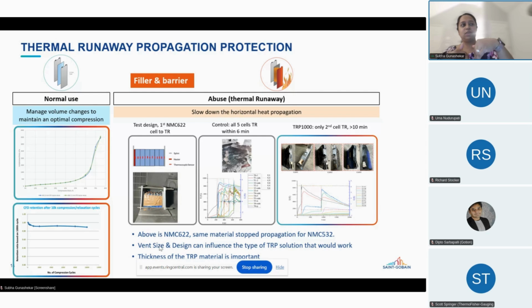So in case of an event, there is still a lot of time for the passengers to get out. So considering all of those, we try to design the right product. And another important thing which we've also found is the TRP material thickness plays an important role. I don't have the value here, but I think 1.5 millimeter was the product which was used here. And then when we repeated this test with a 3.2 millimeter product, it stopped the thermal propagation. So the thickness also plays an important role. These are some factors to consider.